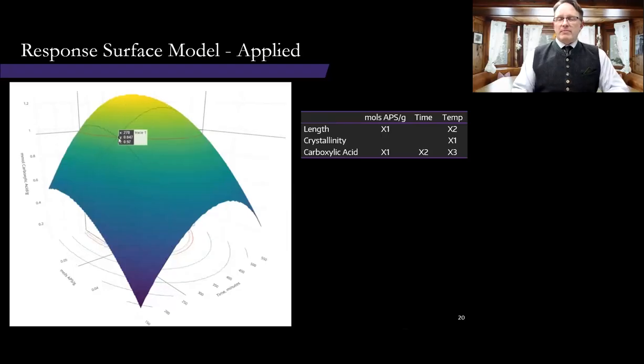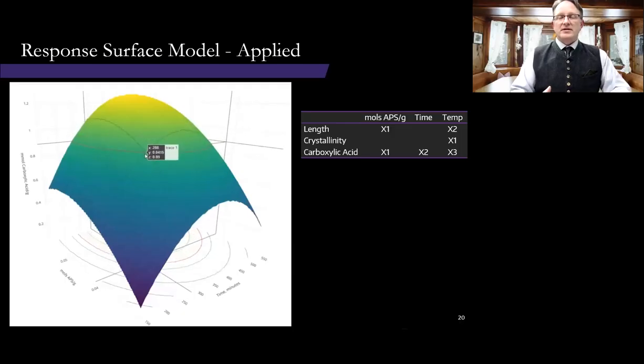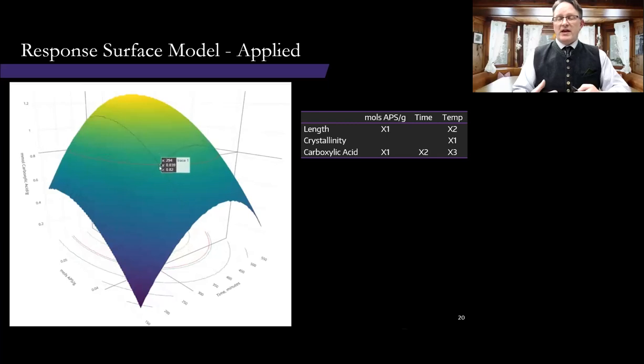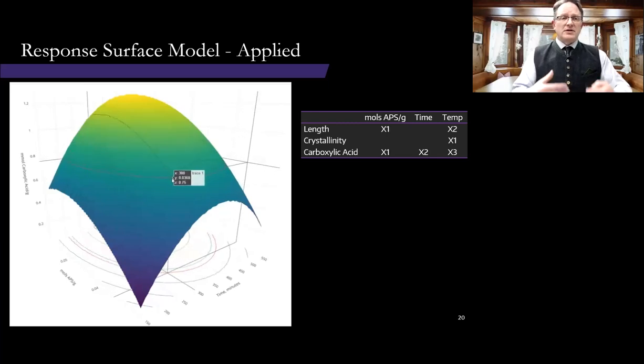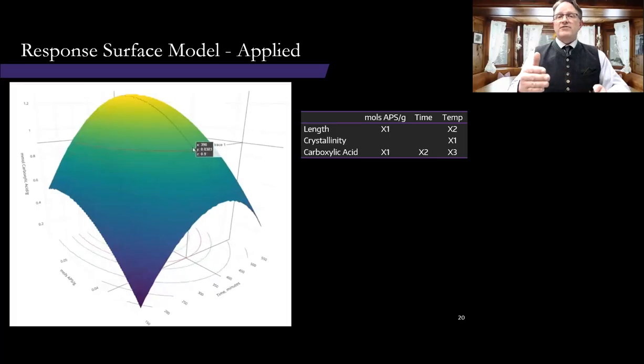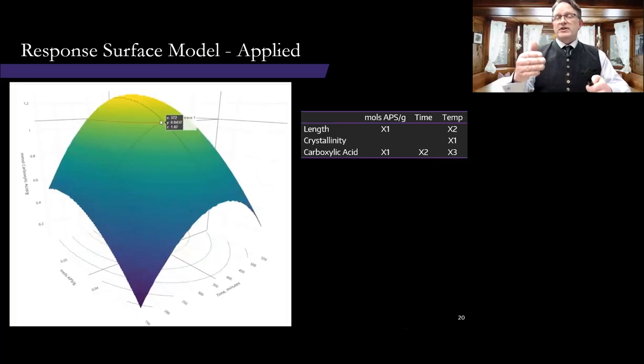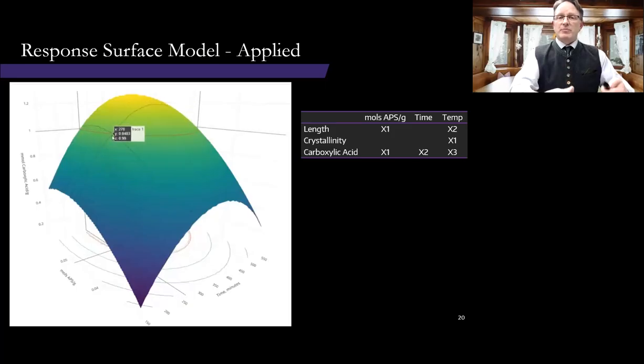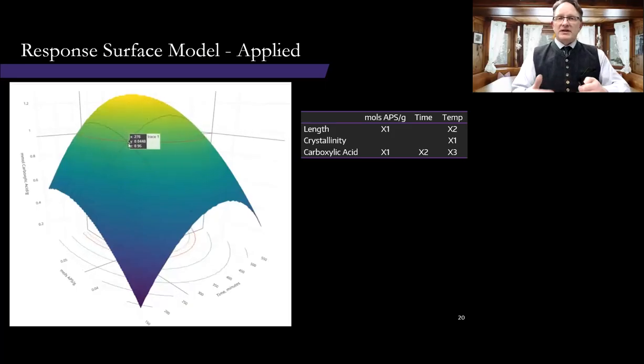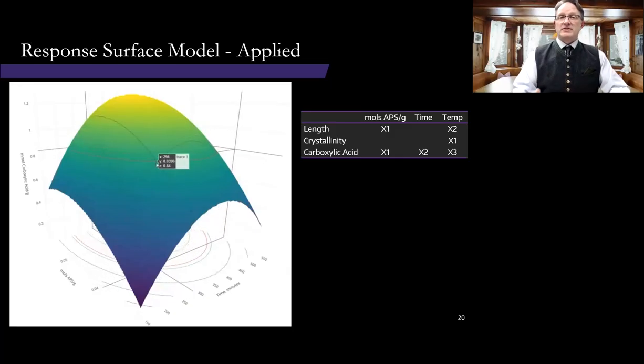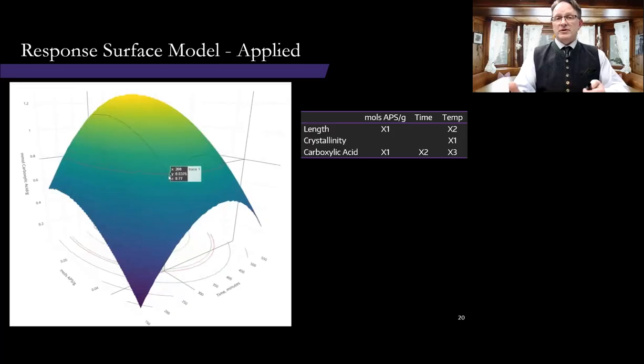So the response surface model, as I stated before, allows us to evaluate the effect that each treatment has on fiber response, and that's the effect that's predicted by the model. In this example, this animation here, I just wanted to show it holding temperature constant, and I move my cursor across the surface. I can identify the specific treatment conditions for that predicted response. In my discussion in part 2, I will demonstrate how I can apply response surface methodology to 2 responses in order to determine what the experimental treatment conditions would be.